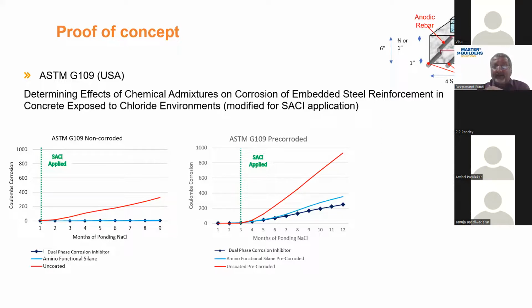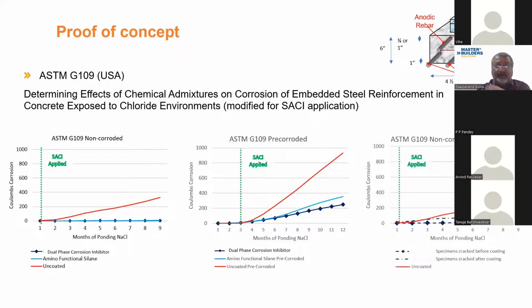In the last graph, you can see non-corroded and cracked concrete. In cracked and uncracked concrete, the untreated portion has pretty high corrosion activity, and in the treated cracked concrete, it is almost zero. This has all been done as per ASTM G109.